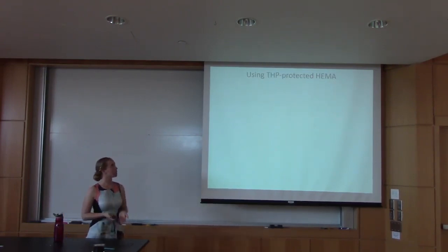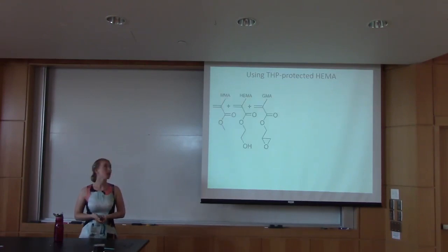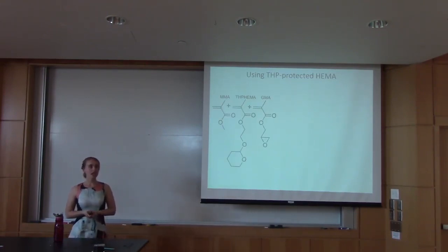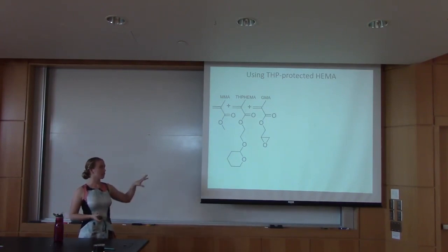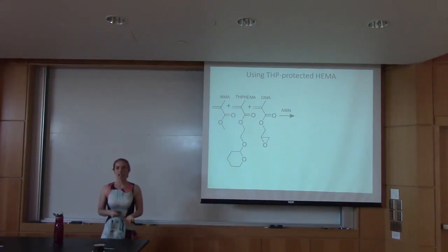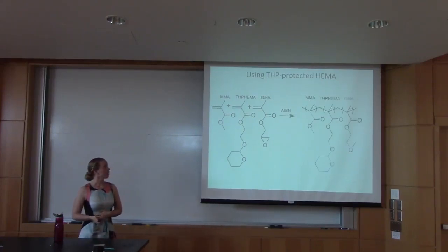So the next thing we tried was using THP protected HEMA. Instead of just having this OH at the bottom of the HEMA, we changed that to this ring group. And so now this ring group cannot react with that GMA. With that, we added our AIBN, our initiator, to start the reaction, and then we got out our THP HEMA with our MMA and GMA random copolymer.